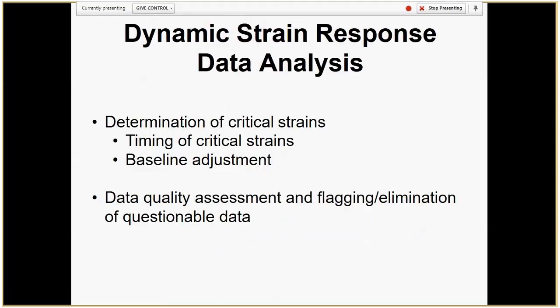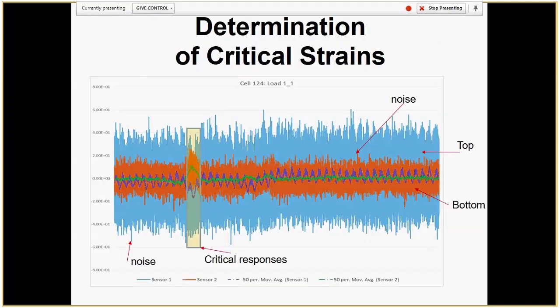So basically, after that, we re-evaluated dynamic strain responses provided to us by MnDOT, and basically we came up with similar conclusions to those achieved by MnDOT, but with some exceptions. First of all, we make sure that we are not accounting for noise when we pick up maximum responses. So we applied several techniques, but the simplest one, we just use moving average to find the approximate window of time of maximum responses, and after that we find the maximum response in that area and subtract the baseline.